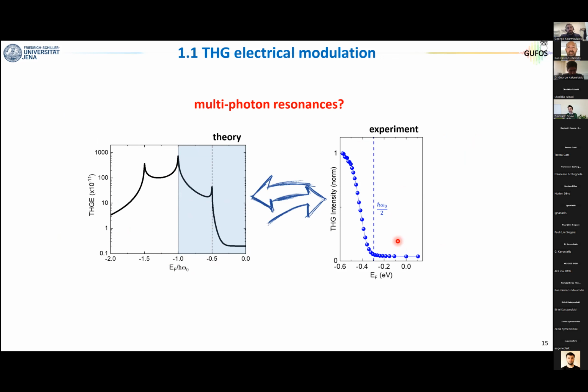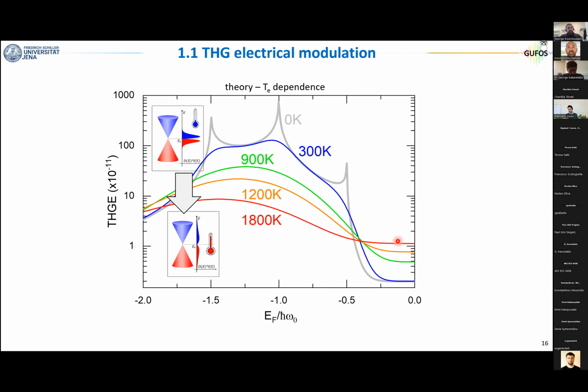And let me tell you that the answer is that something is missing, because until now I was a bit cheating, and the theory that I showed you is developed to work only when the electronic temperature is equal to 0 Kelvin. Now, 0 Kelvin is something that does not exist in experiments. So if you now extend the theory to certain values of the electronic temperature, you get these other colors of the curves, and you can easily understand what is happening by considering that as you increase the electronic temperature, you broaden the Fermi-Dirac distribution, and this broadening broadens these very sharp peaks. They merge into a sort of featureless modulation of the high harmonics.